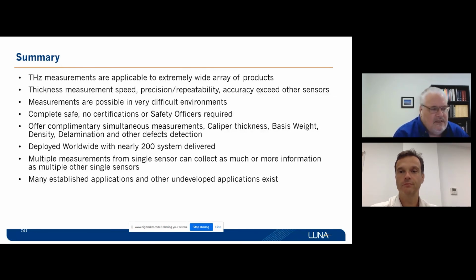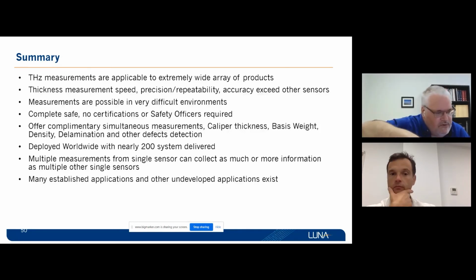But if you don't need to use that, the other way of using it is you pull the trigger, which sort of arms the device, and then you bring it down, and when it senses it's at a distance at which you can see a coating, it simply makes a snapshot measurement and reports the thickness. So if you have a wet coating, you would just hold it over the surface, pull the trigger, and as you slowly lower it down, it will suddenly make the measurement, beep and display the thickness of the coating there when you hit the right distance to the target. And it's not that difficult to accomplish.